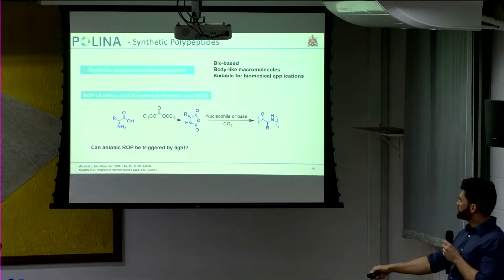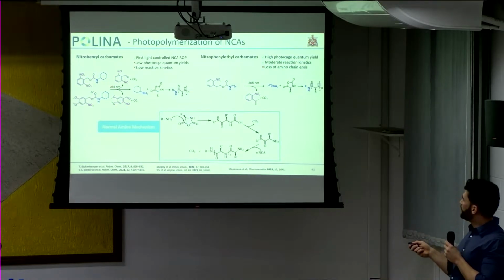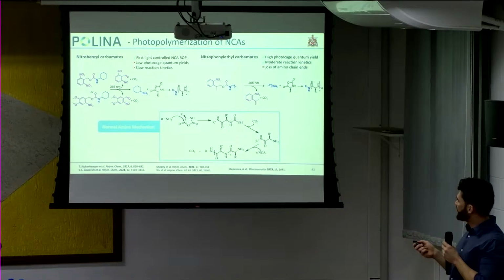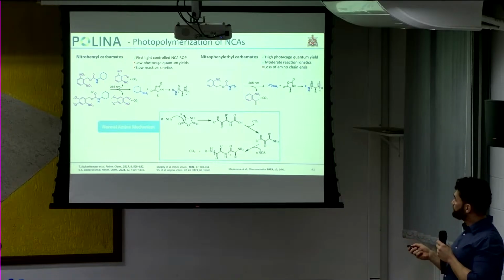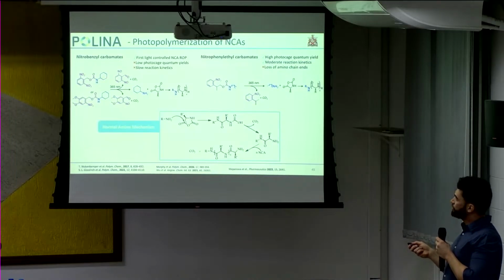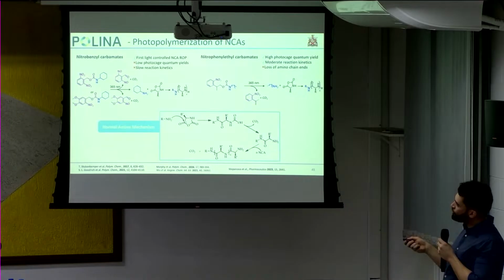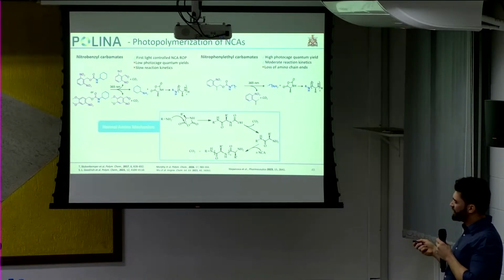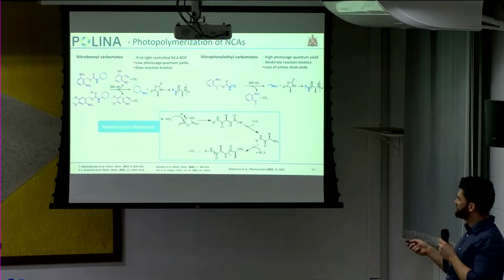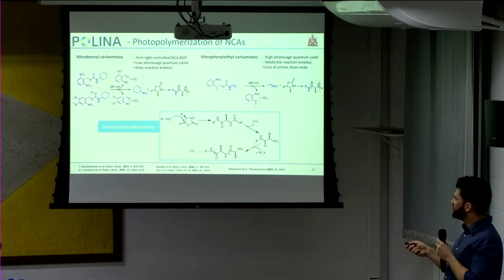The answer is yes, but the first two works to do that used amine photocages, and the quantum yield of the photocage was not that high, which means that the release of the base upon photon absorption was not that good. Also the reaction kinetics was a bit slow or moderate because they use the normal amine mechanism, as the initiator is a nucleophilic base. So how do we go around that?